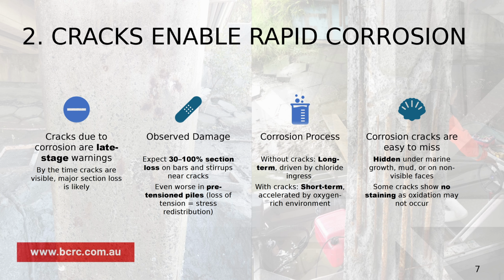But as soon as we have a crack, oxygen gets in and we're dealing with an oxygen-rich environment, which accelerates corrosion many times. And unfortunately, these cracks are very easy to miss, because they're often hiding behind marine growth, mud, or could be simply on non-visible faces. As often happened to me, you would inspect the element or a structure from the shore and it all seems alright, but as soon as you get on a boat, get around, you see these cracks. So pay attention and make sure that you inspect the structure all over. And bear in mind that sometimes you actually won't see the staining.